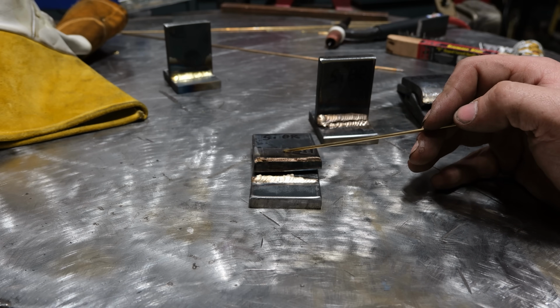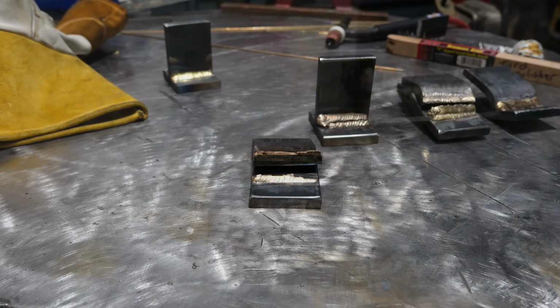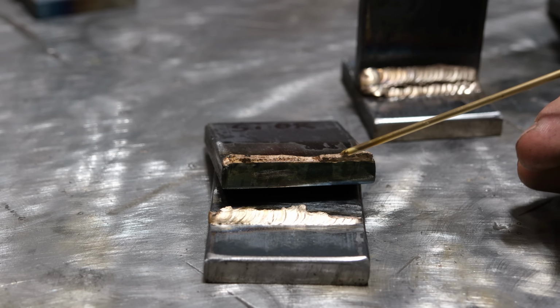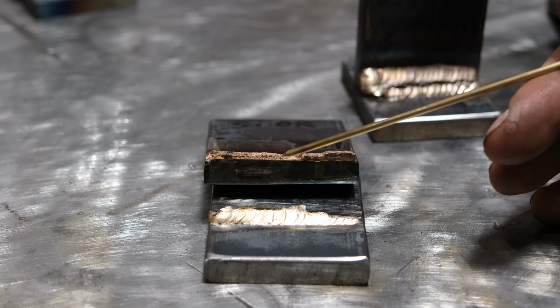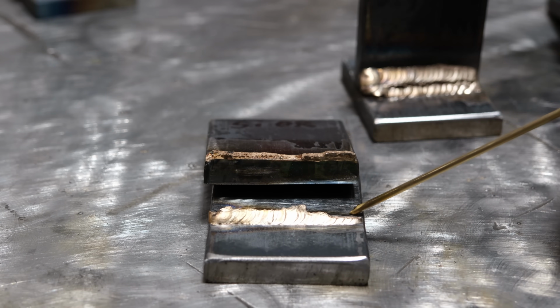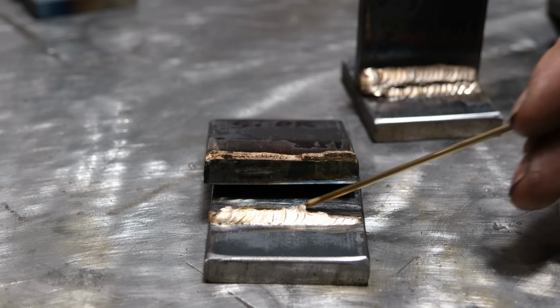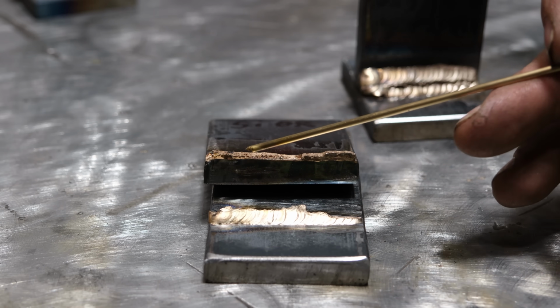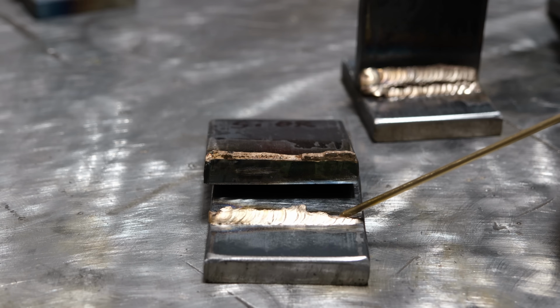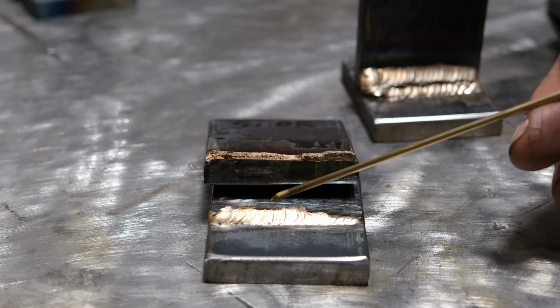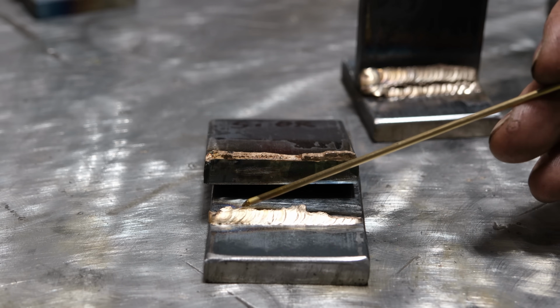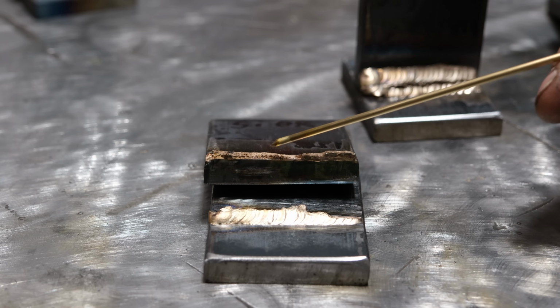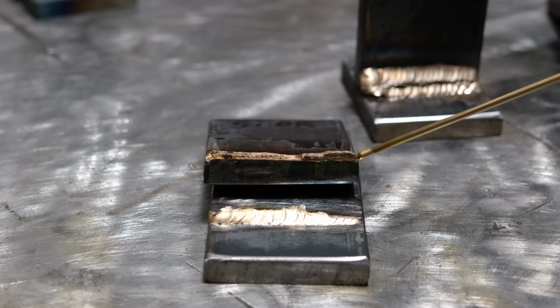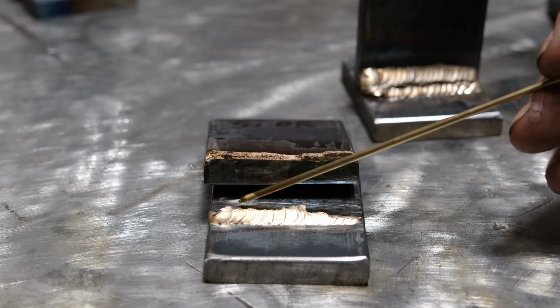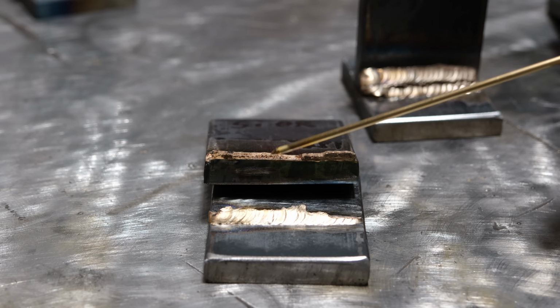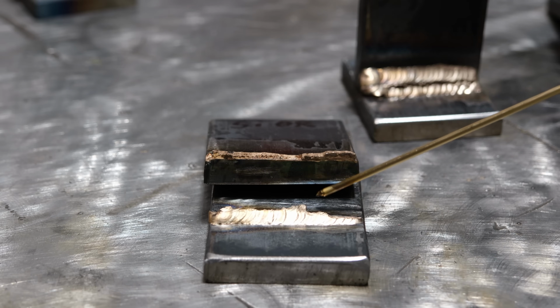Now, the first one we're going to look at is this guy. Let's zoom in. As expected, the braze did not melt any of this original plate edge, and it did not pull any of the material out of this plate whatsoever. This is 100% just a failure of the braze material. In this case, I would say this is as good as it's going to get. It's a single pass. Everything looks good. It's consistent for the depth of, well, we can't call it fusion, but the braze got all the way to the root. Everything looks good.